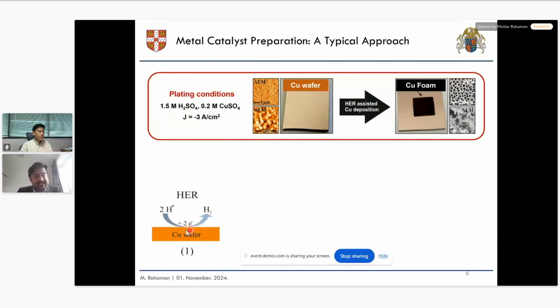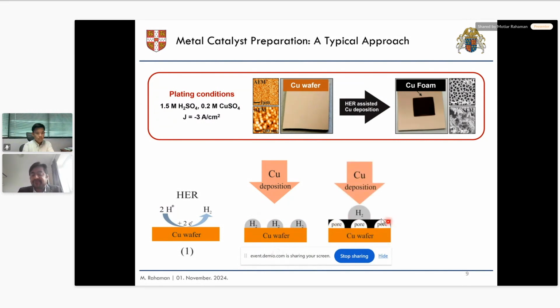In brief, we can see here this is the copper wafer substrate. From the acid, we get protons to hydrogen under a highly cathodic condition. This hydrogen bubble comes on the copper surface, and then copper deposition starts happening just beyond the hydrogen bubbles. And we can see the growth of a nice macrostructure of copper. This black stuff is the growth of our dendritic or macroporous copper material. We have a very nice porous structure of copper on the planar copper wafer substrate, and that is the catalyst. We can use this catalyst for the carbon dioxide conversion process.